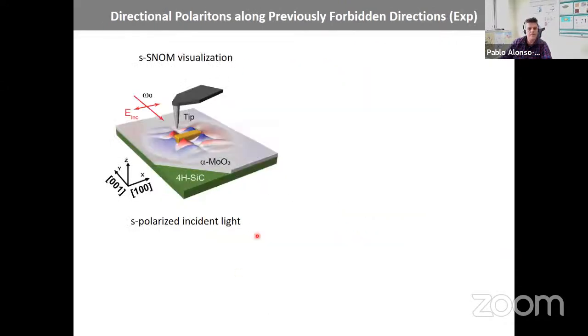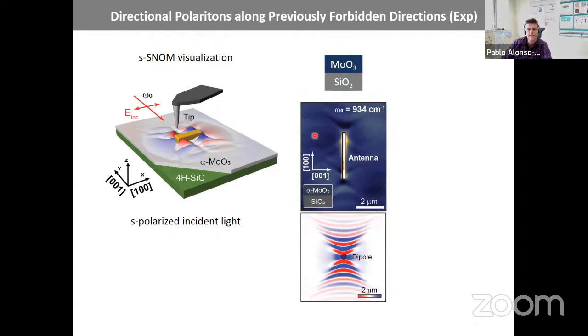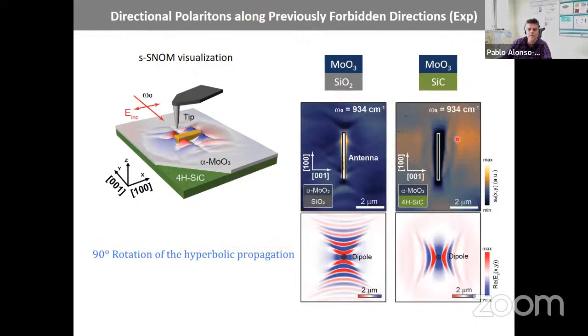So, okay, we did the same experiment. We used a SNOM tip as well. And then we tried to visualize the propagation of these polaritons in MoO3 when it was on top of this particular substrate, silicon carbide, and compared it to the case of silicon dioxide. Here in silicon dioxide we see the typical propagation along the 1, 0, 0 direction. When we put it on silicon carbide, we saw propagation that before was impossible along this other direction. So experimentally, we proved this prediction of our equation.